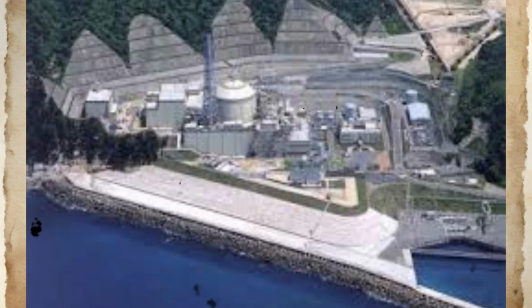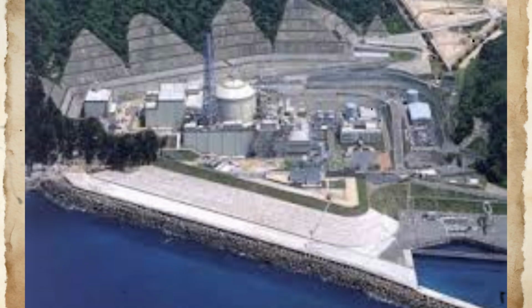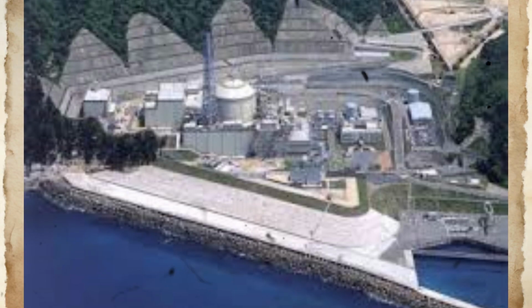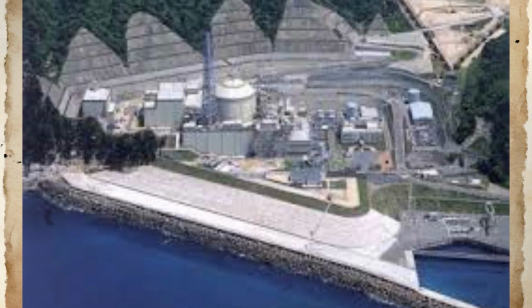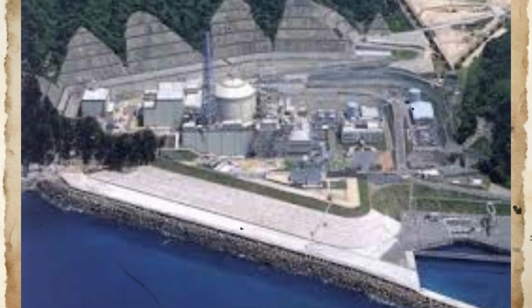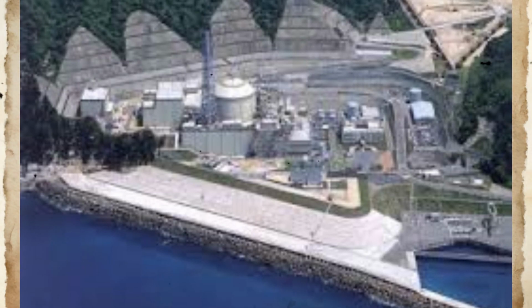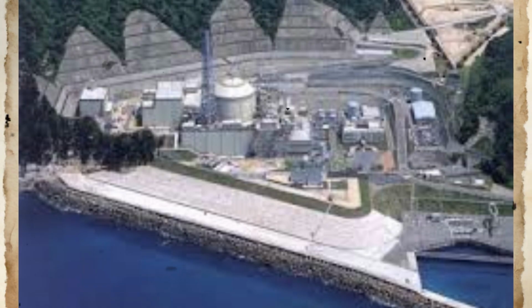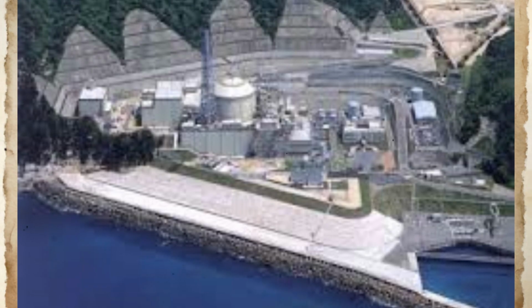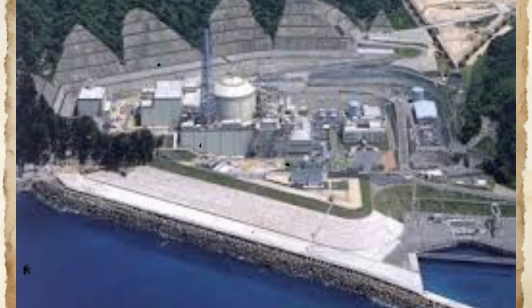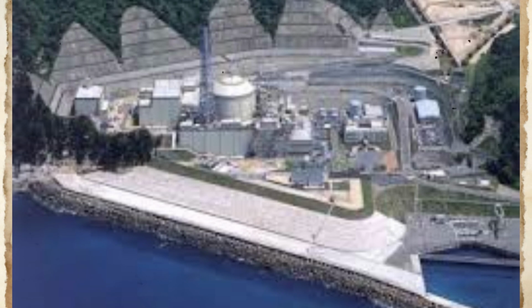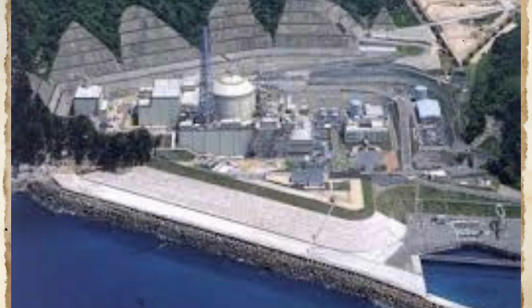This continued normal thermal performance reinforced operator assessment that the leak was relatively small and localized. Major sodium leaks would be expected to cause significant temperature variations as system inventory was lost and thermal balance was disrupted. The absence of major thermal transients suggested that the leak rate was manageable and that system integrity was not seriously compromised. Pressure measurements in SGS Loop C similarly remained within normal operating ranges.